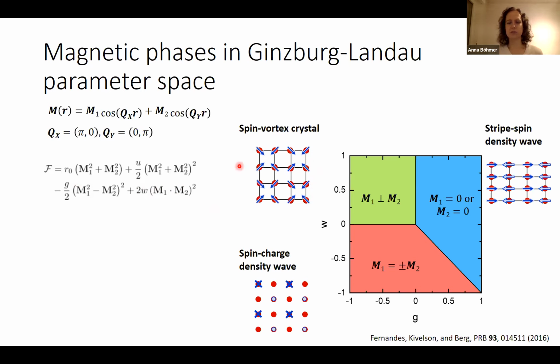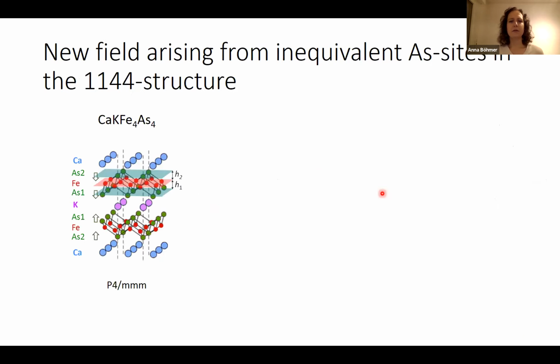There is this spin vortex crystal magnetic order, where the two order parameters are perpendicular to each other. And that's where the non-collinearity comes from. There's another one where they are parallel and of equal size. That's a spin charge density wave, what it's called, or C4 by some experimentalists. But today we are going to talk about this area here. And where does the 1144 structure come in here?